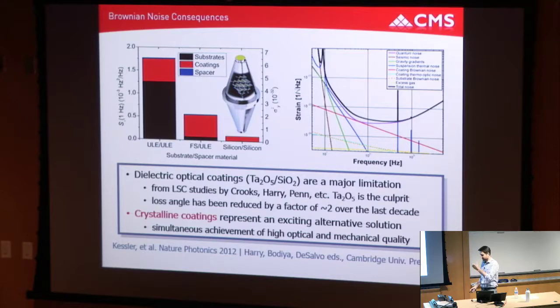And as I mentioned, you saw on that slide, Saulson had looked at this in 1990. In the late 90s, early 2000s, LIGO did a bunch of very methodical work on measuring the quality factor of these coatings. What they found is that they could get excellent optical quality, but it's the high-index tantalum pentoxide films. These mirrors are multilayers of high and low refractive index materials that repeat through. And this high-index tantalum material has a poor mechanical quality factor. This is really the limitation in the system. If you have a perfect glass, you can have high mechanical Qs.